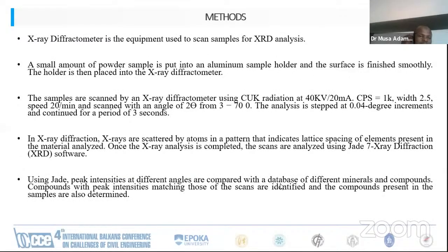So the X-ray diffractometer is used to scan for the XRD analysis. A small amount of powder sample is put into the aluminum sample holder and the surface is finished smoothly. Then the sample is scanned by an X-ray diffractometer using CuK radiation at 40 kilovolts, 20 milliampere. Then the analysis is stepped at 0.04 degrees increment and continues for a period of 3 seconds.